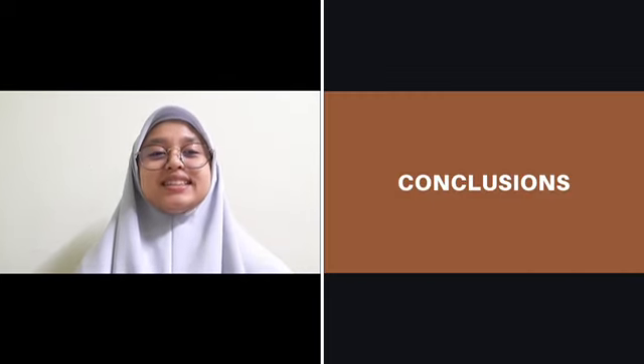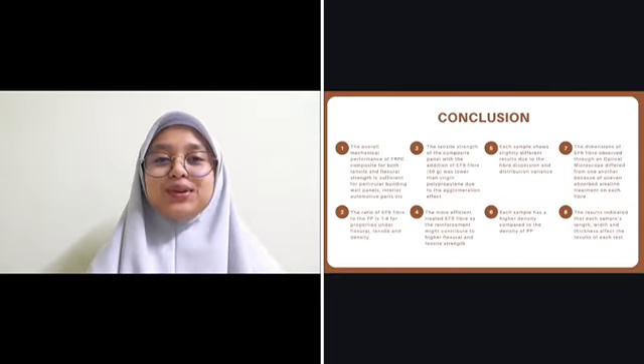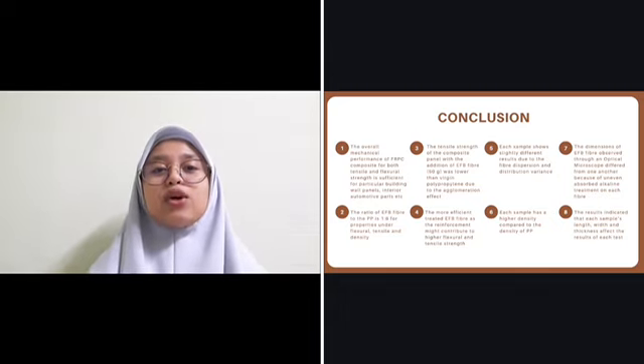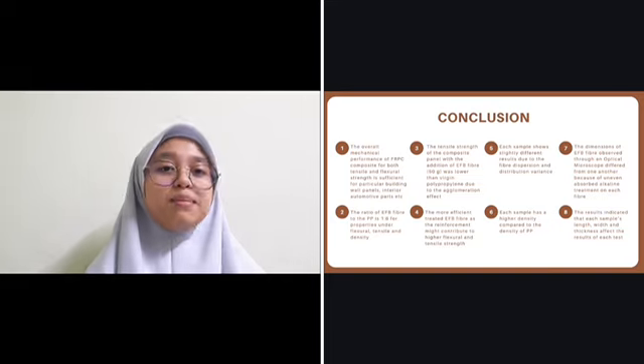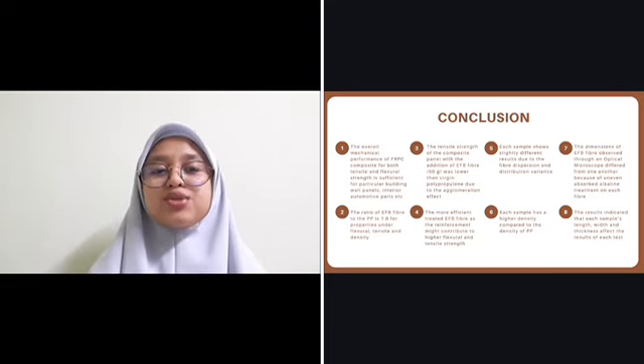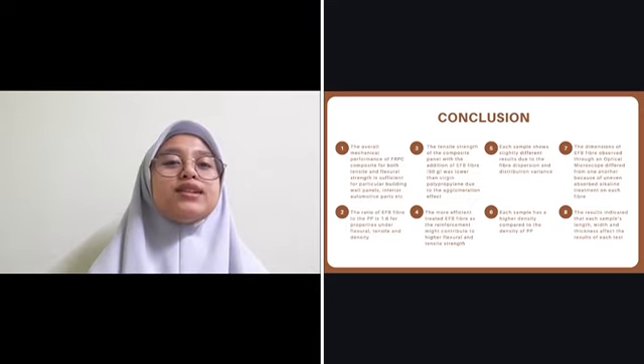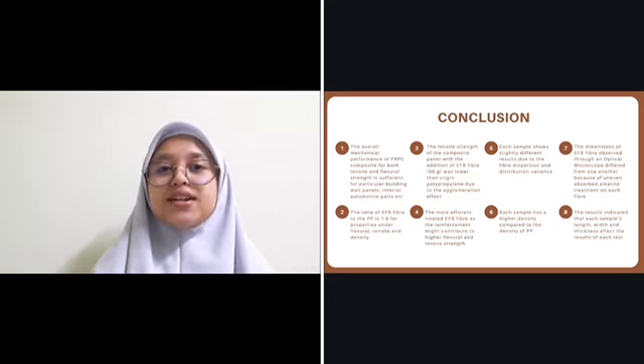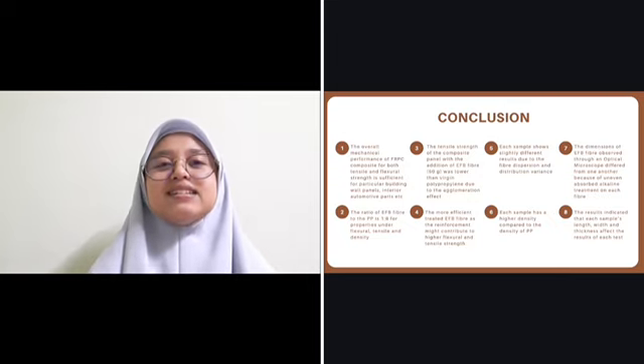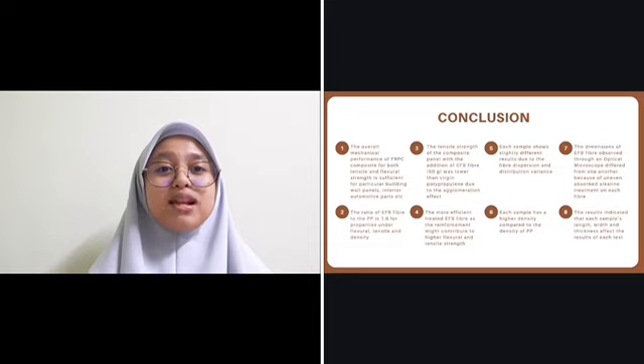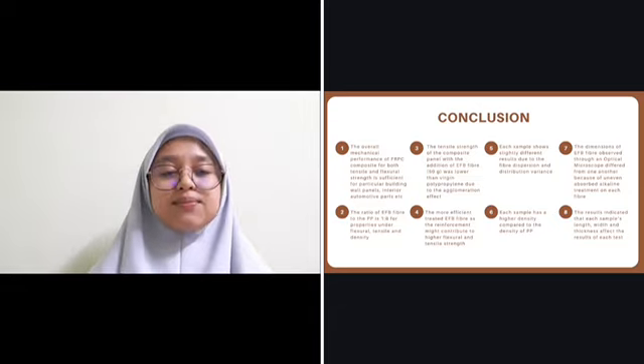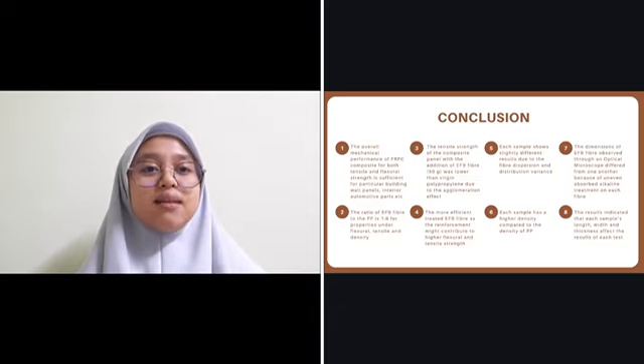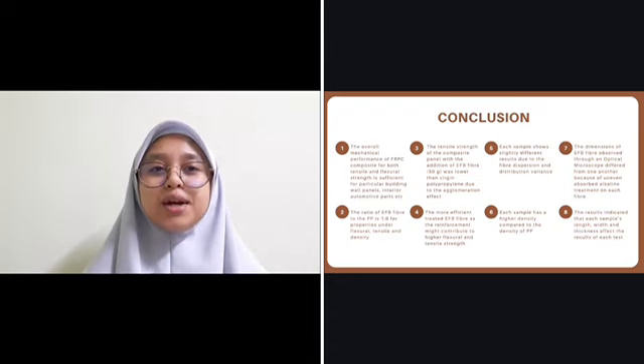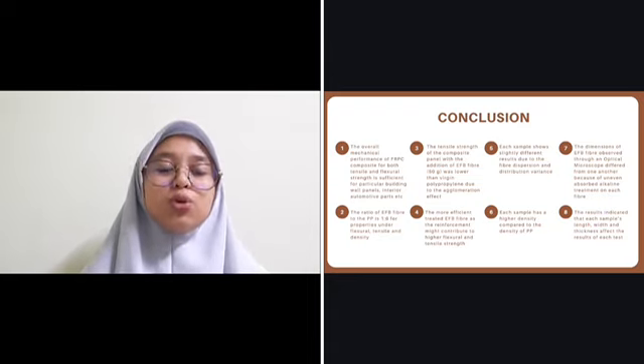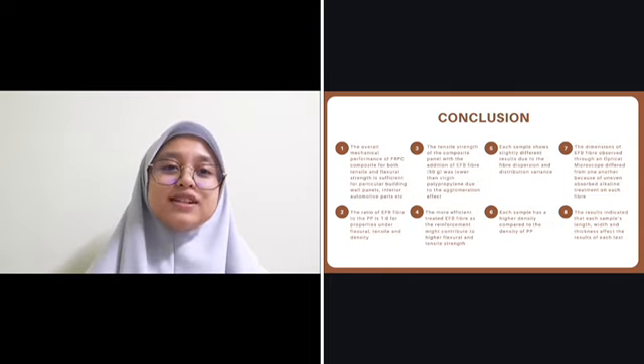Moving on to conclusions. There were 8 conclusions made during this study. The first one is that the overall mechanical performance of FRPC composite for both tensile and flexural strength is sufficient for particular building wall panels, interior automotive parts, and etc. The second, the ratio of EFB fiber to the polypropylene is 1 to 8 for properties under flexural, tensile, and density. The third one, tensile strength of the composite panel with the addition of EFB fiber, which is 60 gram, was lower than virgin polypropylene due to the agglomeration effect.